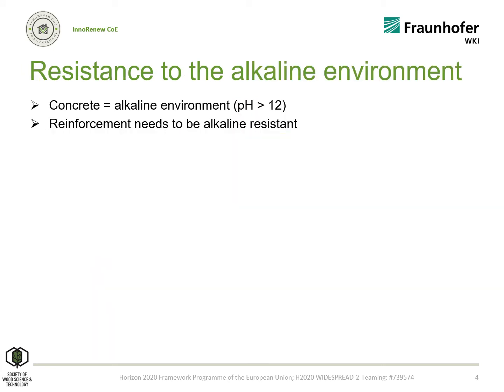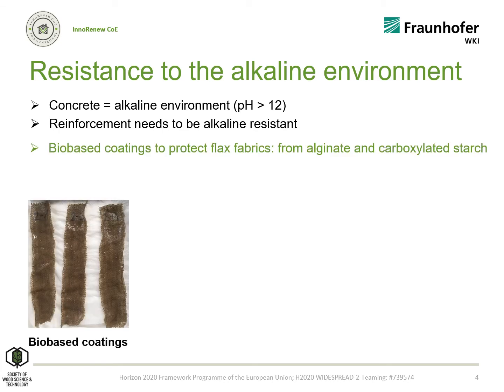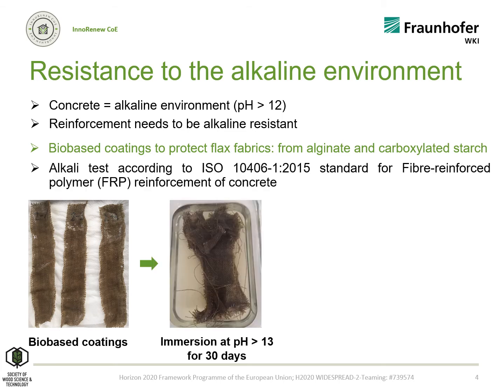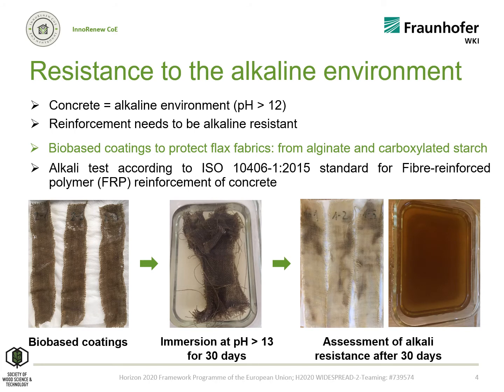The concrete, when it hardens, generates chemical products that create a very alkaline environment, so the reinforcement needs to be alkaline resistant, not to be damaged. Flax fibers are decomposed in alkaline environments, so we used bio-based coating to protect the fabrics. And then we assessed the coatings by immersing the fabrics for 1 month at pH higher than 13.